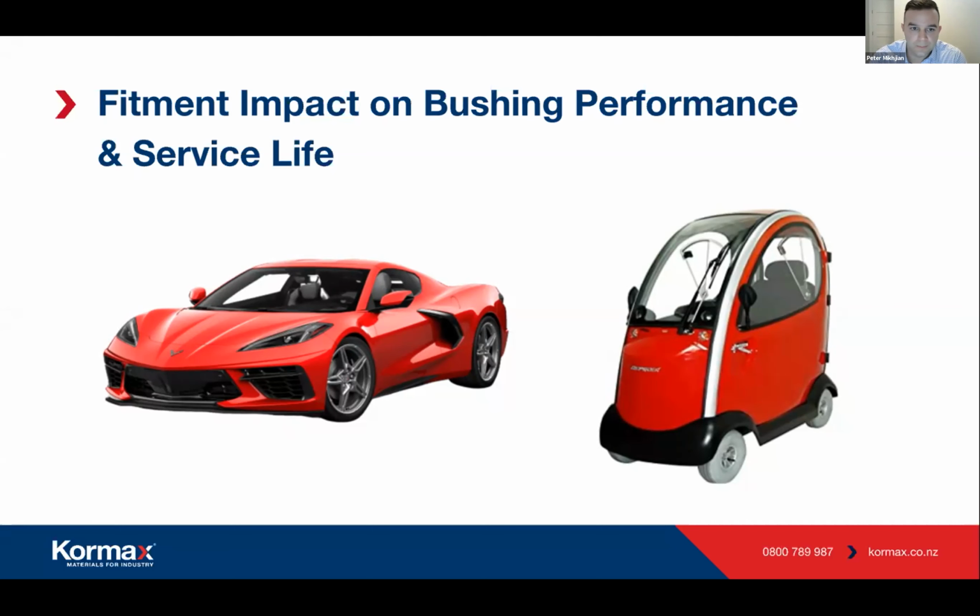So temperature, pressure, and velocity are the 3 main variables that we take into account when designing a bushing. But when we're looking at bushing performance and how the bearing wears and the overall service life, there are other variables that also have an impact. The operation frequency, are you lubricating it? What type of lubricant are you using? How much lubrication are you using? The mating material hardness, surface finishes, clearances, all of these variables impact the service life of the bearing. And the clearance specifically actually has a large impact, but it's also a very easy one for us to control.